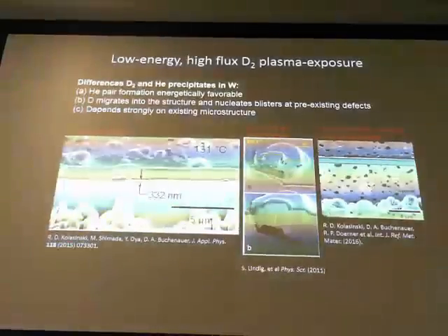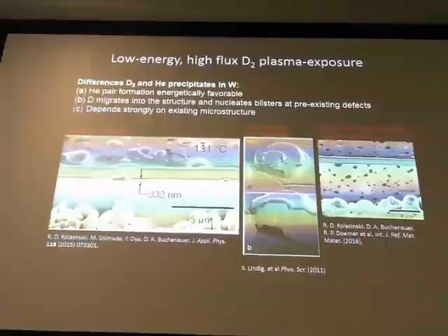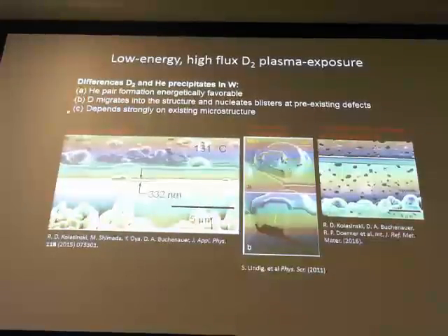And then deuterium plasma exposure, or hydrogen isotope exposure of surfaces, seems to be somewhat different from the helium exposure. The helium pair formation in tungsten is a favorable process. Essentially, two helium atoms in neighboring interstitial sites within a tungsten lattice are energetically favorable to form a stable pair and then eventually form a tungsten self-interstitial. But that's not the case for deuterium.